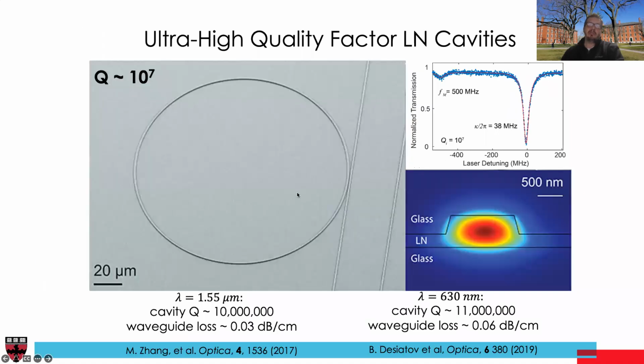First, we wanted to demonstrate that high quality factor lithium niobate resonators are possible, because this is one of the precursors to reduce the threshold for frequency comb generation. So here's some already 5 years old work that shows that ultra high quality factor lithium niobate cavities with Qs of about 10 million at telecom wavelength can be done. By the way, we have a recent development where we measured material limitations of this thin film lithium niobate, and we predict it's on the order of 200 million. And this is some work in collaboration with Kippenberg's group in Lausanne.